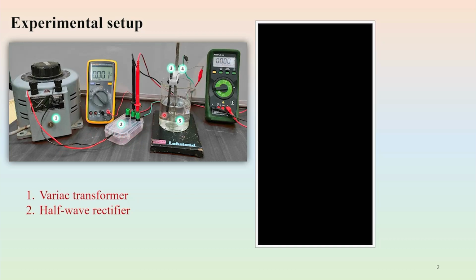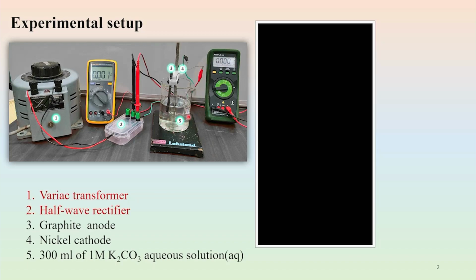Here you can see we have used a 6 mm diameter graphite rod of 99.99% carbon composition for all electrolysis at different voltages, and 1 mm diameter nickel wire of 99.5% nickel and 0.5% iron composition is used as the cathode. We used a 1 molar potassium carbonate aqueous solution. Current and voltages are monitored during the reaction.